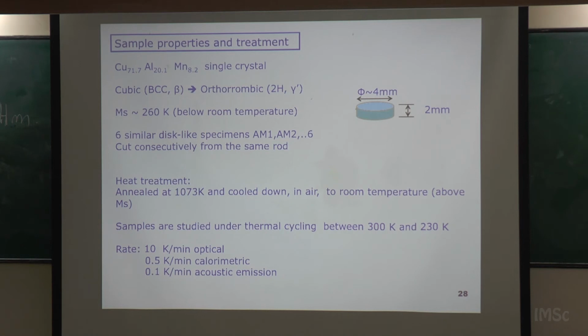The sample is very small. Usually for acoustic emission, we use small samples because, in fact, we want the sample to be of a size similar to the sensor to get as much energy as possible, okay? And we had different samples, well, different specimens, but from the same sample, we cut different discs. They were this size here.